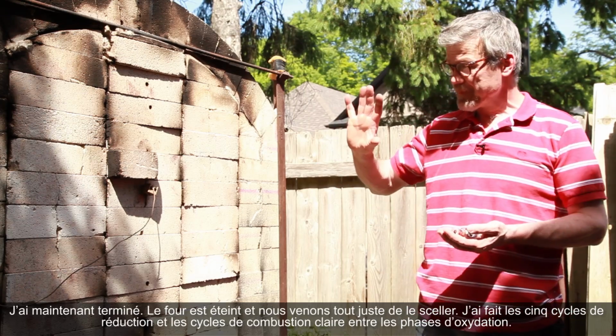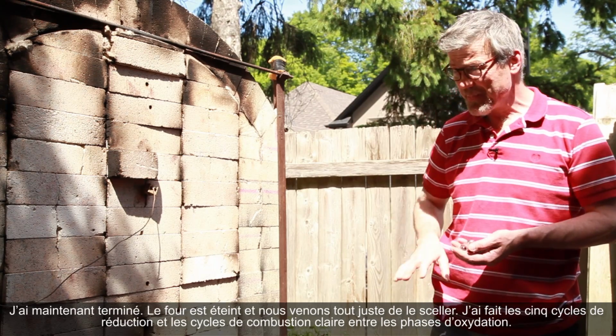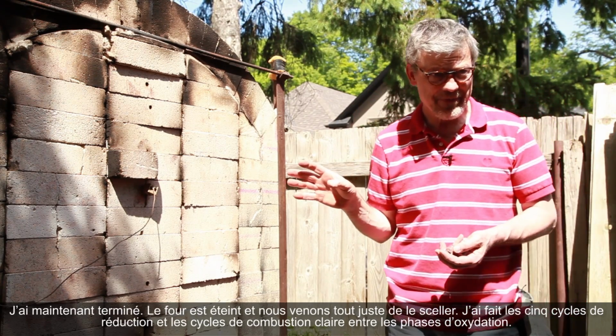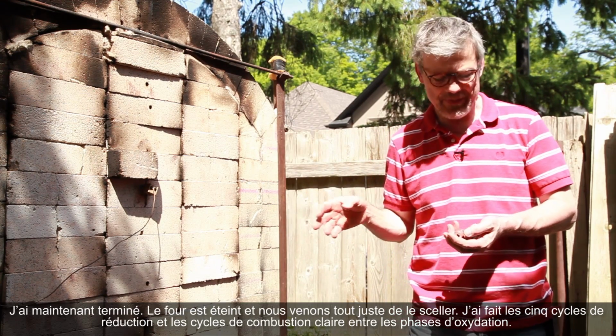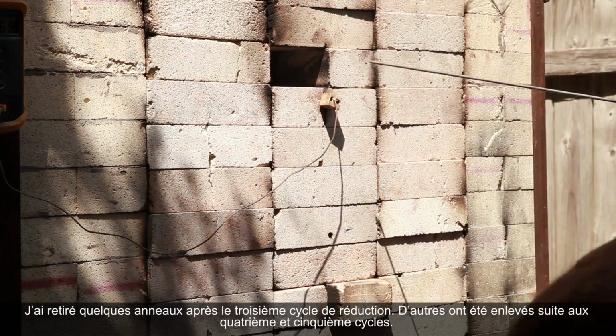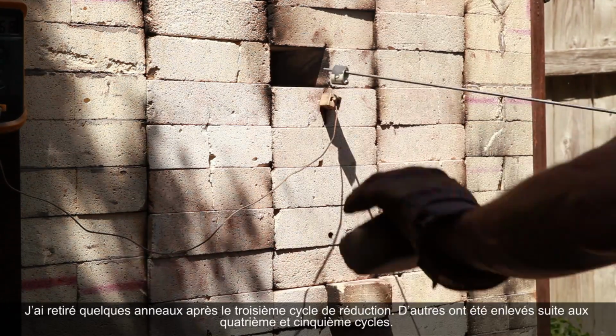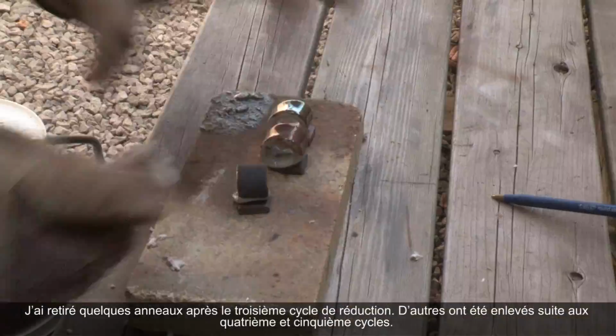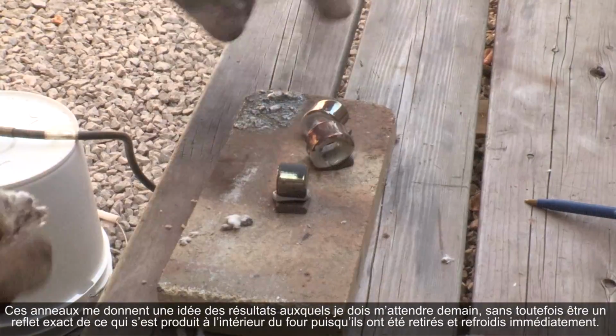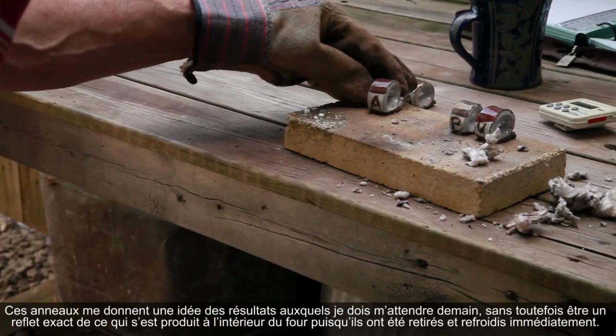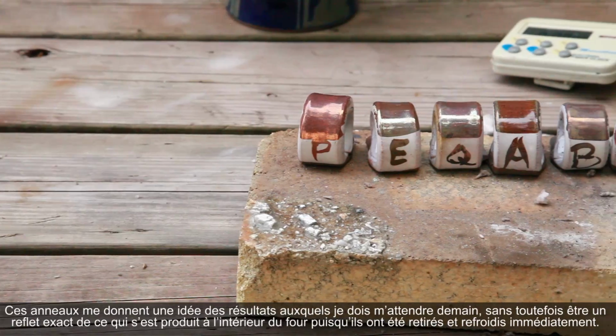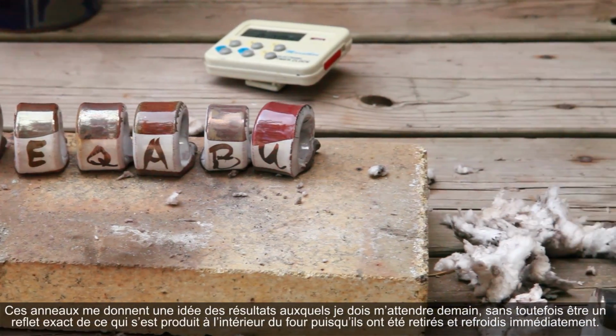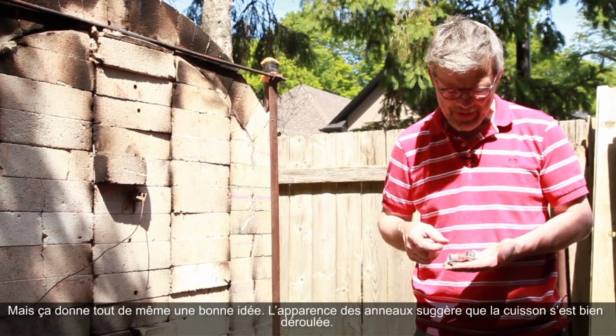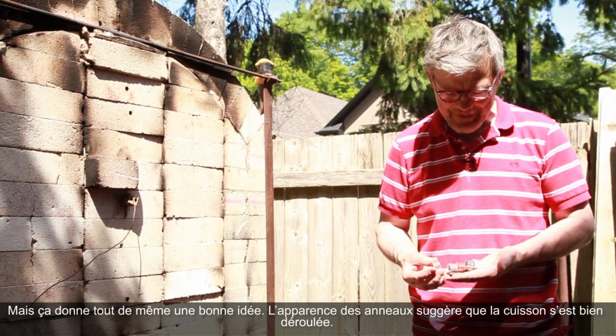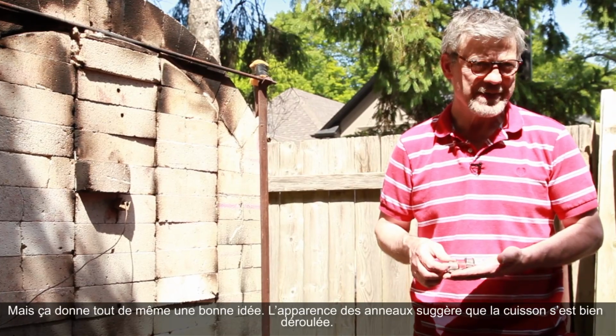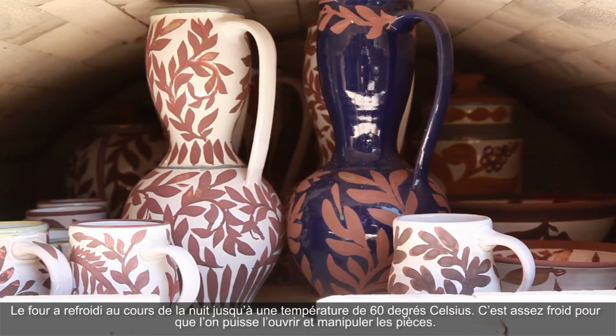Okay, so I'm done. The kiln's off. We've just sealed it up. I've done all 5 cycles of reduction and the clear burning cycles in between of oxidation. After the 3rd reduction cycle, I pulled some rings, and then again the 4th and the 5th at the end. Of course, you want to see them all. And these give me an indication of the kind of results I could anticipate tomorrow. So this isn't exactly what will have happened inside the kiln because these were pulled out and cooled immediately. But they give one an indication, and from the reading of the rings, I think we've got a pretty good result inside.